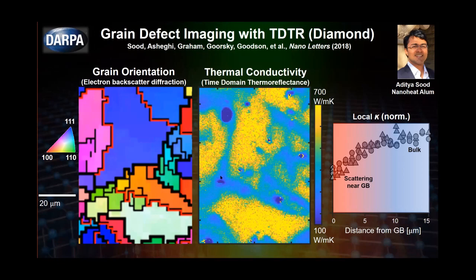Whereas when you approach the edge of a grain, you end up with lower values of the conductivity because the phonons that are transporting through the grains are scattering off those interfaces. Very elegant measurement. And he was able to quantify how that scattering works. And that scanning technique was very innovative and challenging to put together.